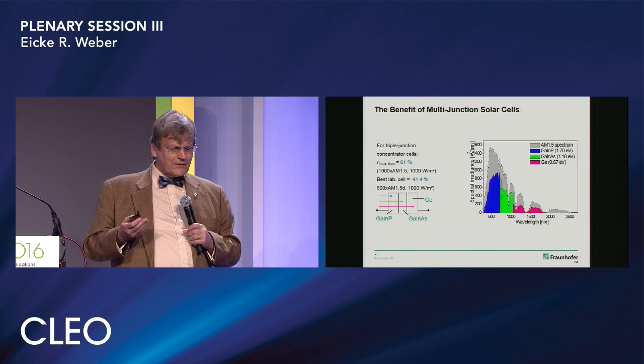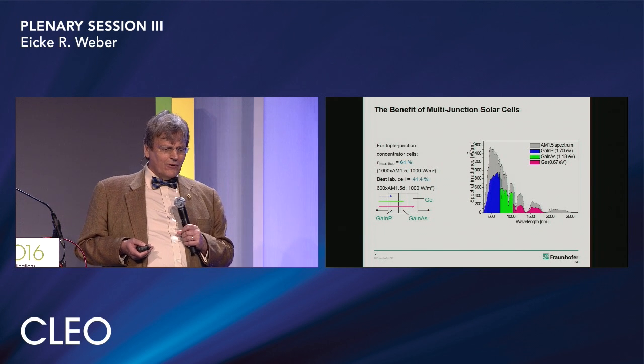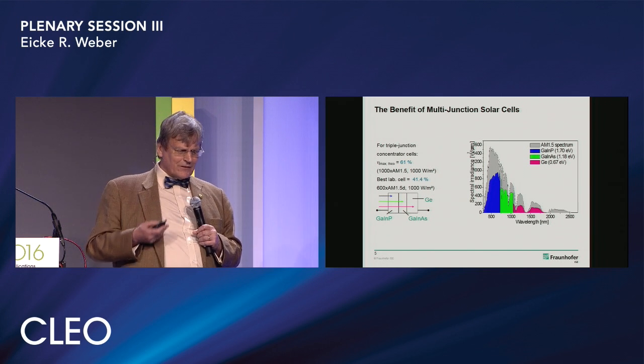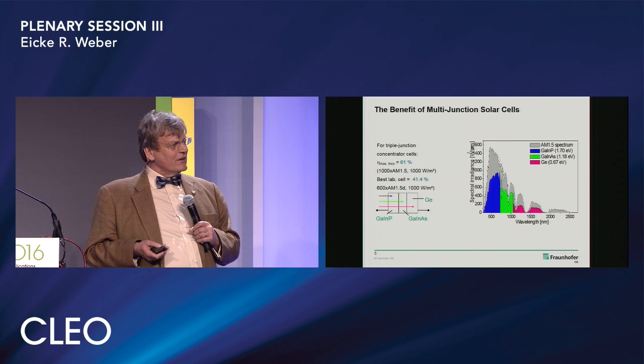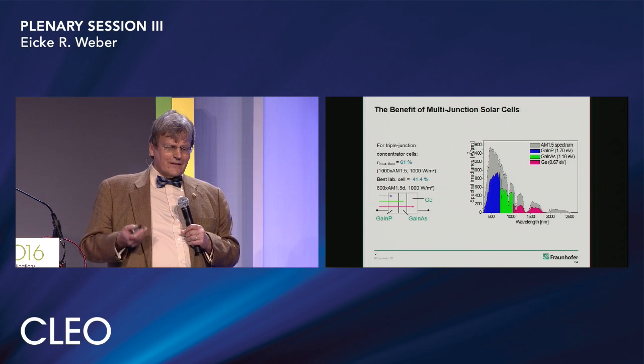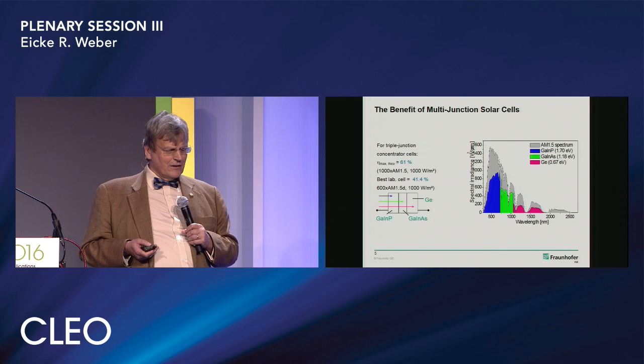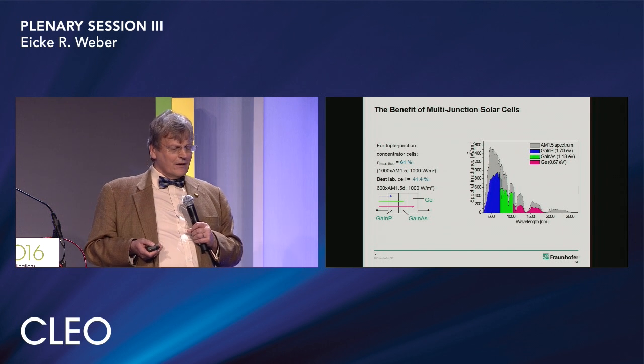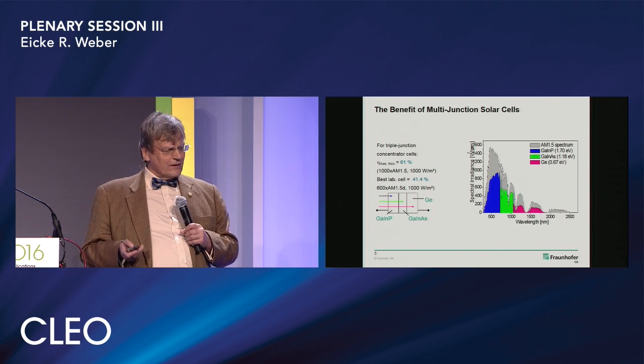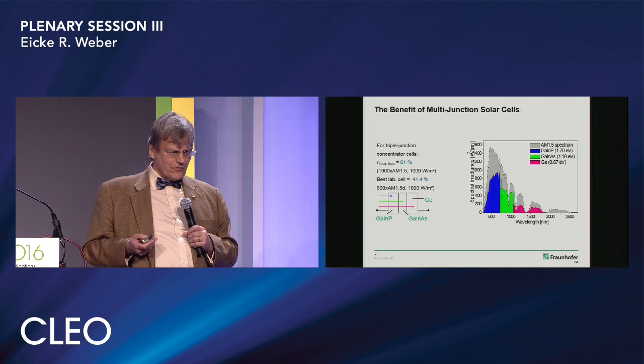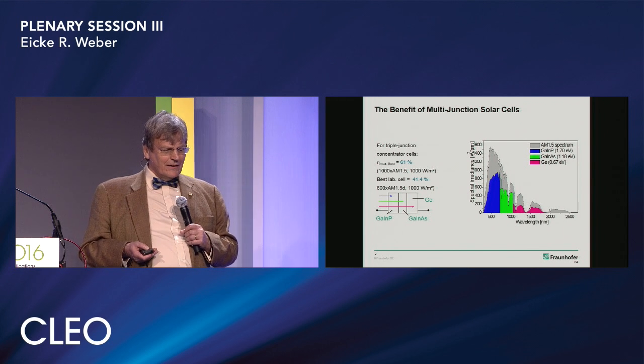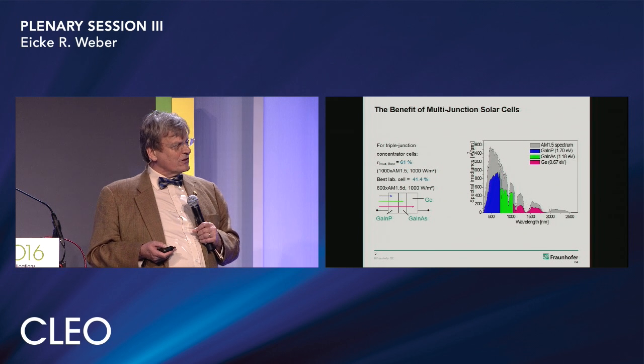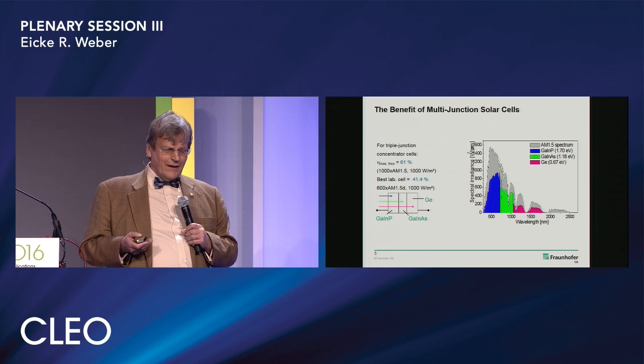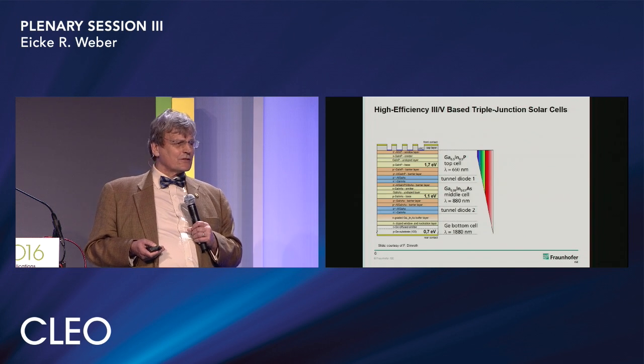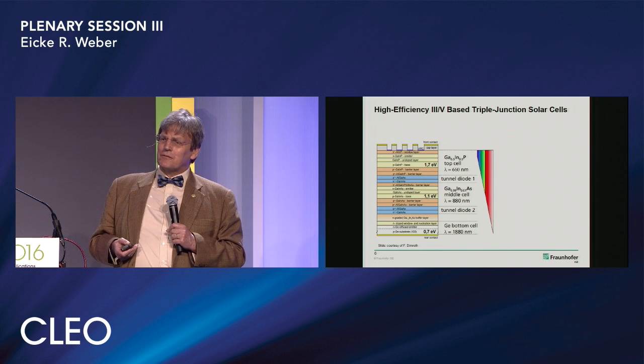One of the structures which is very popular by now are triple junction structures, like the one shown here, based on a germanium substrate, and then gallium indium arsenide and gallium indium phosphide can be grown, and this can achieve already pretty impressive efficiencies. The best lab cell with a triple junction, 41.4%. The problem of these structures is, of course, they're extremely expensive to grow.